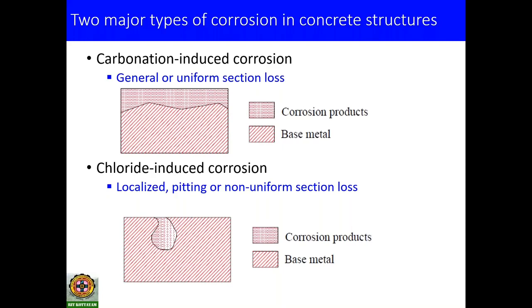The second condition is the presence of chlorides. In chloride induced corrosion, which especially happens in a marine environment or in an environment subject to de-icing salt, the chloride ions enter the reinforced concrete system through the cover of the concrete. They reach the steel rebar, and when the amount of chlorides present on that surface exceeds a particular value, which we call the critical chloride threshold,